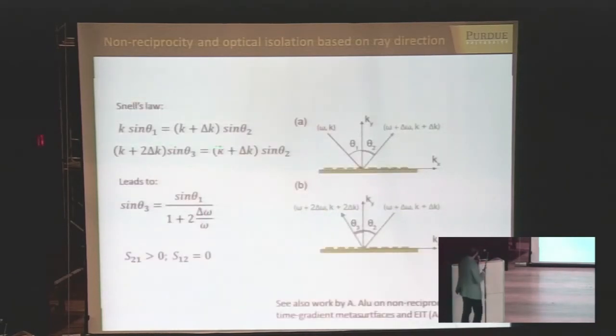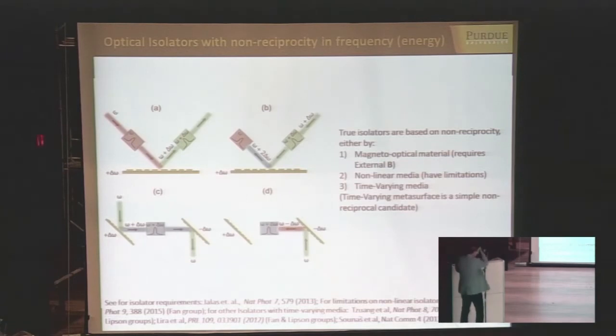So if you look at Snell's law in this case, because frequency changes, K also changes. When it's incident at this angle, it would be reflected at this angle, but when you send it back, it would not go in the same direction. It would be, instead of plus delta K, you'd get minus delta K. So if you have two ports, 1 and 2, you could send it from port 1 to port 2, but if you send it in the opposite direction, it would not go in the same direction. It would be redirected. Or you could do it in the frequency domain.